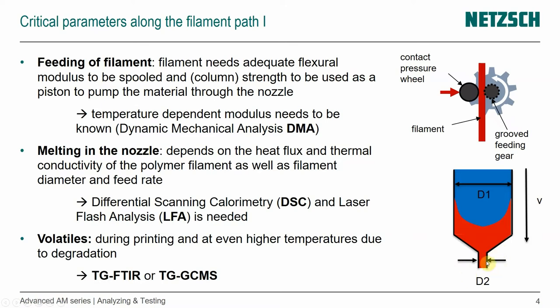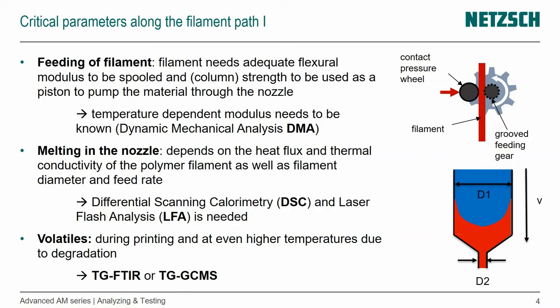Then we're interested in what volatiles come out at the end of the nozzle. Because material extrusion printers are so widely used in home environments, there is more concern than in an industrial setting about how you get rid of the vapors and fumes — you normally don't have exhaust. The volatiles are important, and we can use coupled evolved gas methods such as TG-FTIR or TG-GCMS. Check out the 3D Printing Myth Explained videos if you're interested in understanding that better.